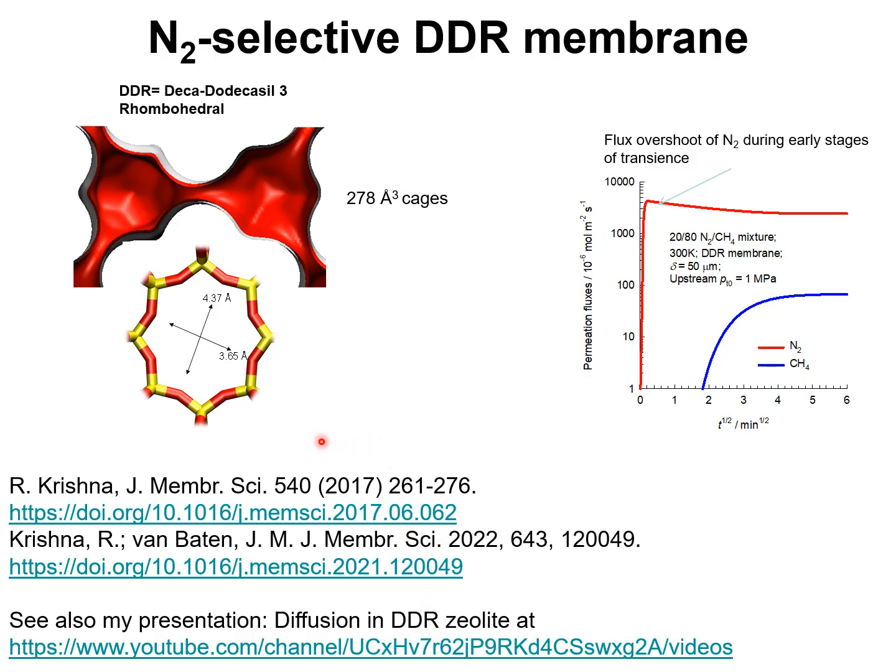Methane, on the other hand, that has a molecular dimension of approximately 3.7 angstrom, is severely restrained and cannot jump from one cage to the adjacent cage as frequently as nitrogen. The permeation selectivity is largely dictated by the diffusion selectivity that favors nitrogen.